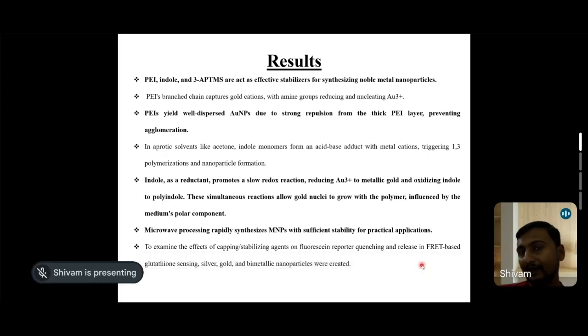In aprotic solvents like acetone, indole monomer forms an acid-base adduct with metal cations, triggering 1,3 polymerization and nanoparticle formation. So for the first time we have also introduced the indole as a reducing as well as stabilizing agent of gold nanoparticle. Further, indole acts as a reducing agent, promotes slow redox reaction by reducing the gold cation to metallic gold and oxidizing to polyindole. These simultaneous reactions allow gold nuclei to grow with a polymer influenced by the medium polar component